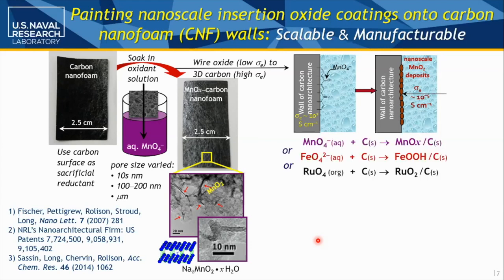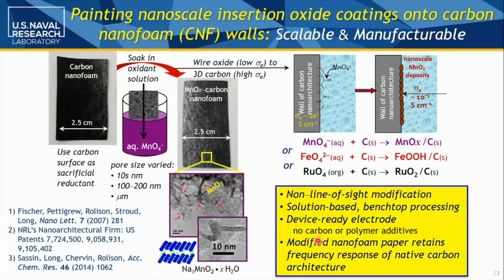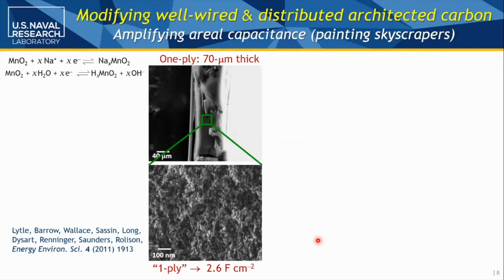And the important thing about doing it with this controlled, if you will, painting is that you're not carpeting the boundary of the paper with thick manganese oxide. And that allows you to design in the pore structure that designs in your frequency response, and now you've added a more interesting redox flavored system on top of this carbon fiber paper. So Megan Sassin took a 1-ply, 2-ply, 3-ply system, cross-sectioned it, looked at it in the microscope with the manganese oxide on there. And again, we're going to stay aqueous. So we're either going to be something like a sodium sulfate or a lithium sulfate, a mild electrolyte, not strongly acidic or basic. And so in a sodium sulfate system, you're potentially inserting sodium. And if you've got water around, you always have to remember proton is often the preferred insertion ion.